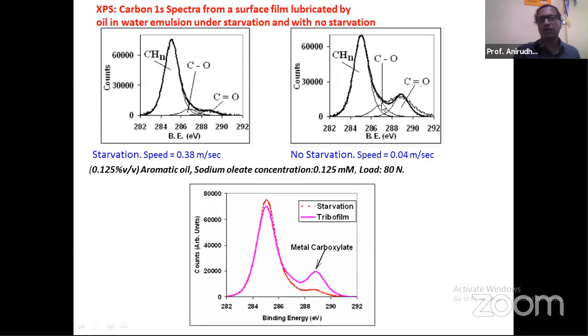Now, I have superposed these two XPS data below and shown in color just to make it evident that what is actually making this film more lubricious, what is making this film have less coefficient of friction, is the presence of this metal carboxylate which gets formed, and that is something that we have detected from our XPS data. The actual reason for that C double bonded O formation is a metal carboxylate. We should know that this is a tribological application involving a metal, which in this case was iron. Then there was a hydrocarbon because we were using oil in water emulsion, and there was water.